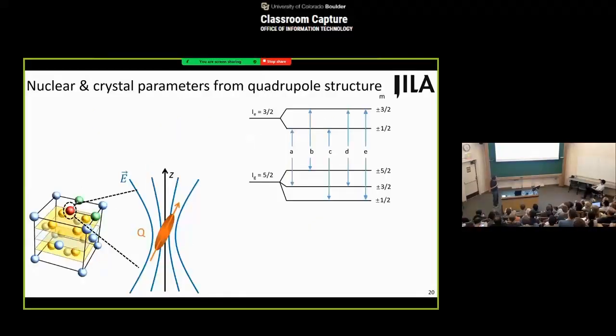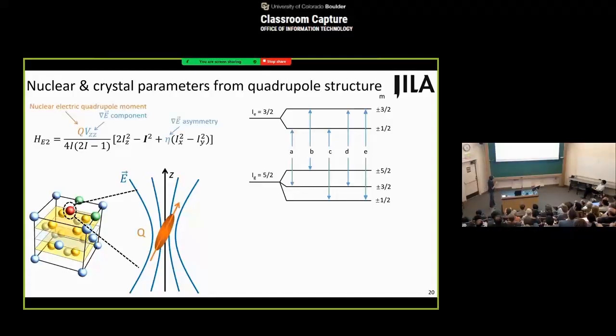Now, we also try to understand the quadrupole splitting better. Essentially, in our crystal lattice, the neighboring ions produce an electric field gradient at the position of the thorium nucleus, and the thorium nucleus has an electric quadrupole moment that could align in different directions in this electric field gradient. So we can write down the Hamiltonian that describes this interaction, where Q is the nuclear quadrupole moment, and the electric field gradient can be determined by 2 parameters: VZZ, which is the principal axis component, and eta, an asymmetry parameter that describes how asymmetric this electric field gradient is.